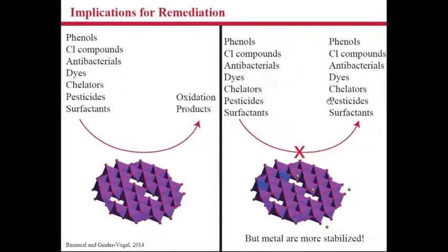If these metals are adsorbed to the surfaces, the manganese oxides may not react anywhere near as quickly, since the metals may shut down the rates of electron transfer. But this is an important side benefit: if the manganese oxides were to oxidize these organic compounds, they would be reduced to manganese 2, which is soluble, and the oxides would fall apart and release whatever metals were held. So by shutting down these oxidation rates, at least the metals are stuck with the manganese oxides.